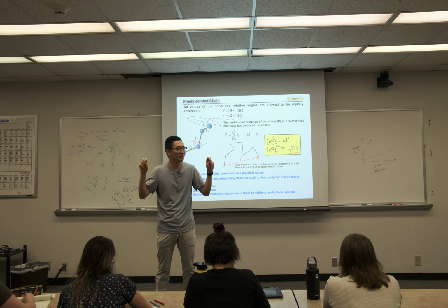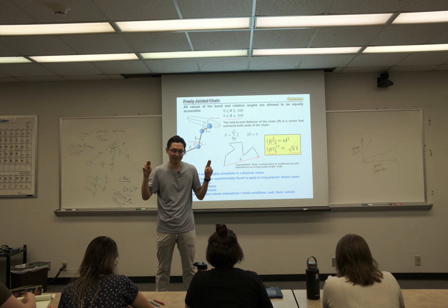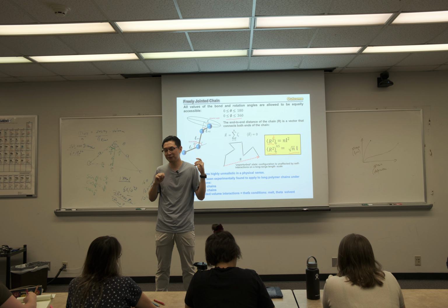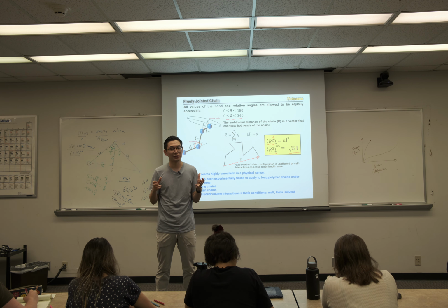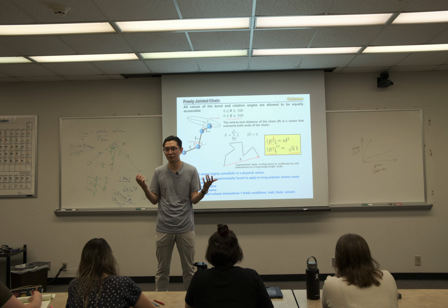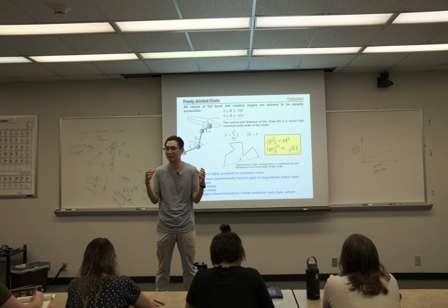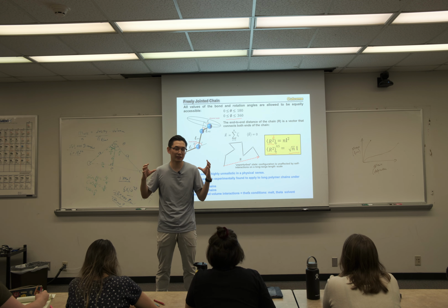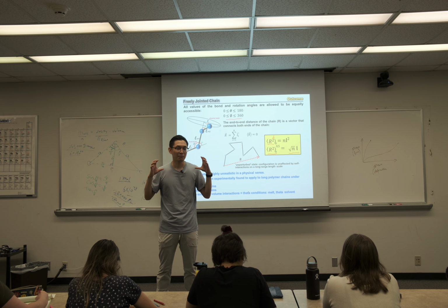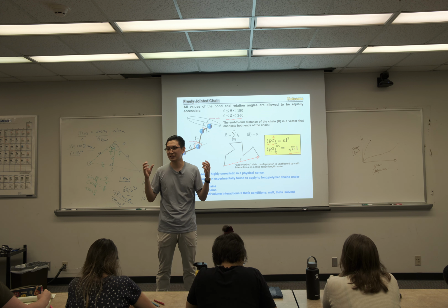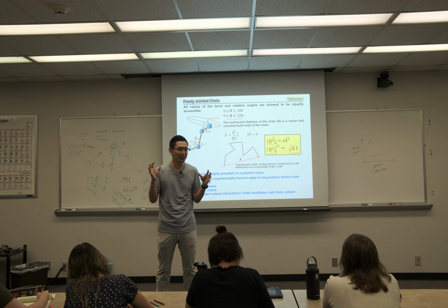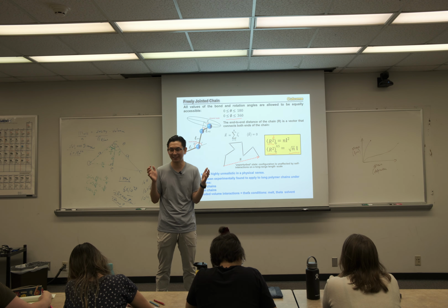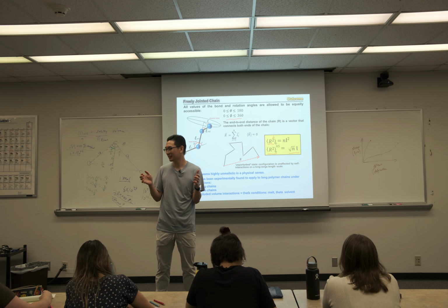And case one, I would never imagine it. Case one would be if your polymer is not dissolved in a solution. So we talked about when it's dissolved, the polymer chains will push each other and expand, so your end-to-end distance will be bigger than a freely jointed chain. But if you dry out the solvent, all of a sudden, the chain behaves exactly like a Gaussian chain or freely jointed chain.